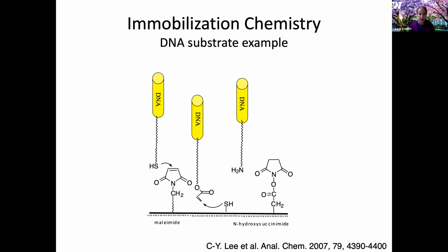So a lot of my initial work was done on that kind of immobilization chemistry. I did this actually in industry, and then I brought it back to academia when I came to academia, where you'll have some sort of a substrate bond, some sort of functional group. It could be a silane system. It could be a thiol gold type system, and then eventually make some sort of functional groups on the surface that then can be bound to something that was on the DNA, and somehow you get the DNA spotted on the surface.